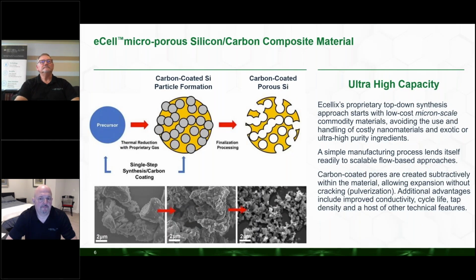So how do we do this? Well, as I said before, the challenge that we have is as we're driving lithium into silicon, it expands. Then when we take the lithium out of silicon, it contracts. As that happens, that material will crack. It also, as it cracks, exposes more surface area of the silicon, which leads to a series of reactions that we don't like to have in the battery.